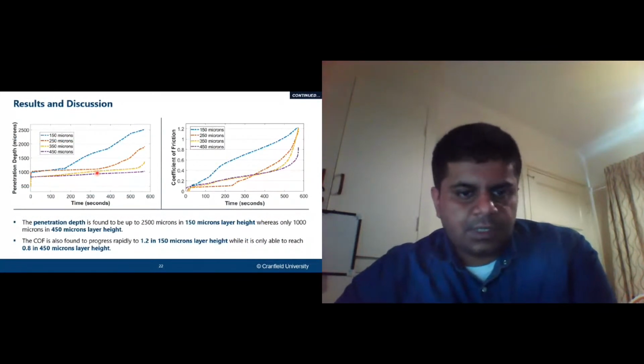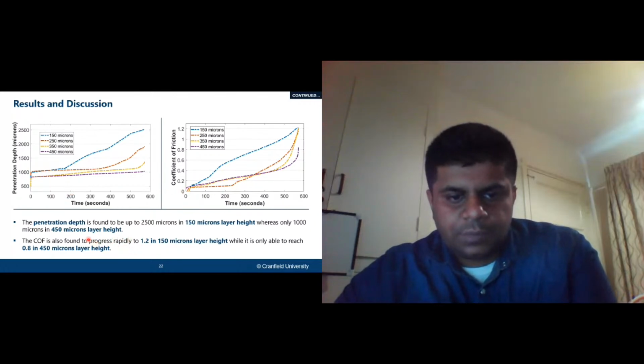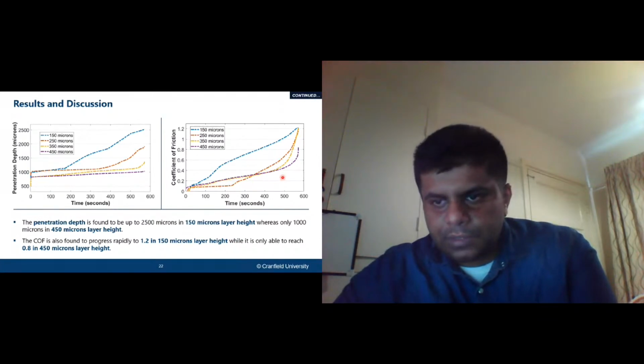So coming on to the results, the penetration depth is found to be up to 2500 microns in 150 microns layer height, whereas only 1000 microns in 450 microns as shown over here. With regard to coefficient of friction, it is also found to progress rapidly to 1.2 in 150 micron, which is this blue line, while it is slower in 450 micron layer height as shown over here. Before 500 seconds, the 450 micron layer height is quite sturdy, but after 500 seconds, we see this sharp trend. So basically, the top layer was more or less eroded, and now the bottom surface started interacting with the ball. So that is why you see this particular trend over here.